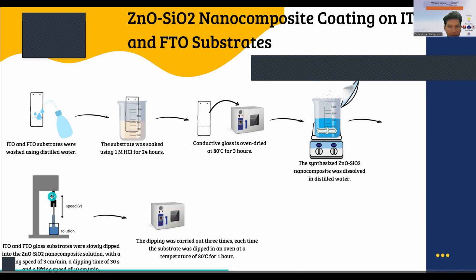Next step, after the mixture was thoroughly dispersed, the ITO and FTO glass substrates were slowly dipped into the ZnO-SiO2 nanocomposite solution at a dipping speed of 3 centimeters per minute with a dipping time of 30 seconds and an uplifting speed of 10 centimeters per minute. After the dip, the layer was dried in an oven at 80 degrees for 1 hour. The deposition was repeated 3 times. Finally, the ZnO-SiO2 nanocomposite layer was calcined at 500 degrees.